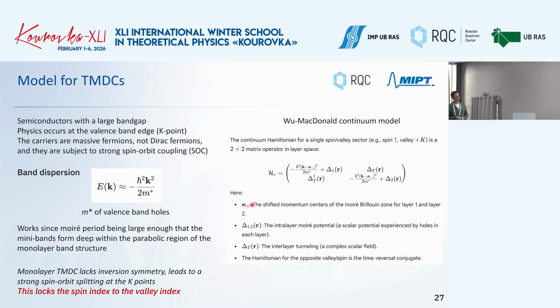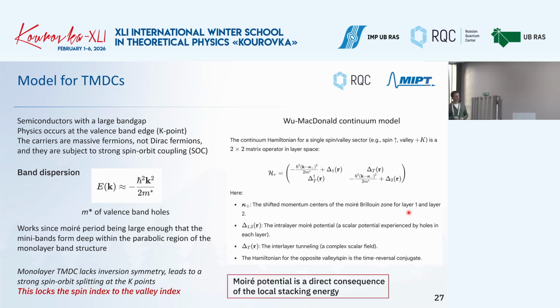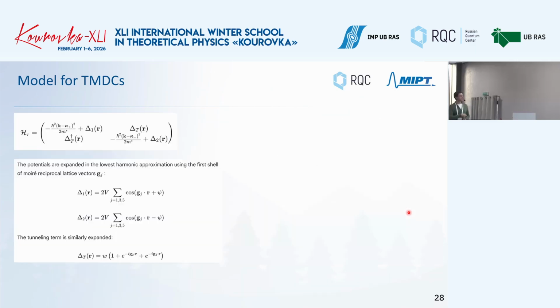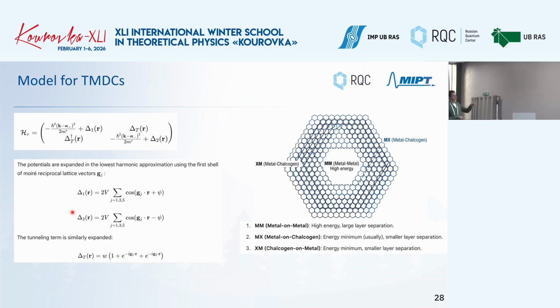So there is an intralayer moiré potential, a scalar potential experienced by holes in each layer. And also there is interlayer tunneling, a complex scalar field describing the tunneling between the layers. So the moiré potential is a direct consequence of local stacking energy. And just a few words regarding the Hamiltonian. So once again, it looks like this. The different potentials I explained in this lowest harmonic approximation. And the tunneling term is described like this. So the important thing is that, first of all, the Hamiltonian looks like this.